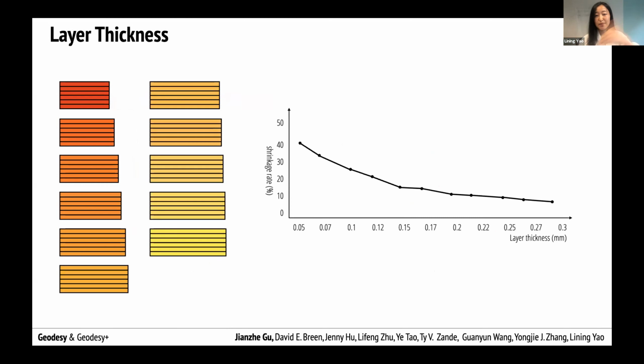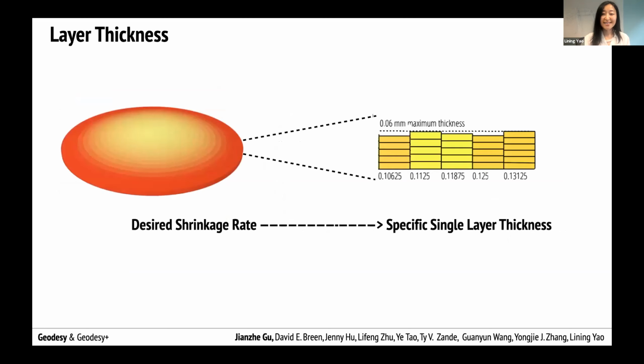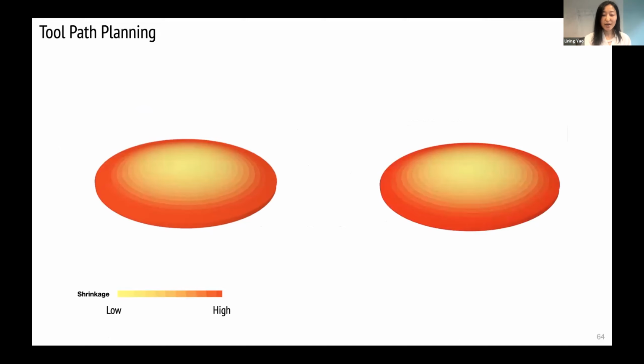So then we can plot the data and try to get this. It's non-linear, but we can get a relationship between each individual layer thickness and the shrinkage ratio of each local region. And then you can now print the disk, but you imagine the printing process pretty much as you are printing X and Y, your Z is constantly adjusting according to the local shrinkage ratio requirement calculated in our computational model. Then by the end, you can print a disk that has local controllable shrinkage ratio, and it will morph in the way we can predict.